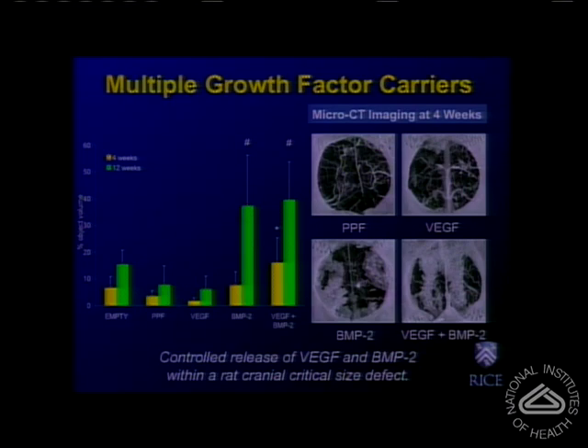So here, this is the 8 millimeter defect. We can image new bone formation and also blood vessels. This is 4 weeks after implantation. This is the case of a polymer by itself, a polypropylene fumarate. With the delivery of the vascular endothelial growth factor, we don't see much bone formation.